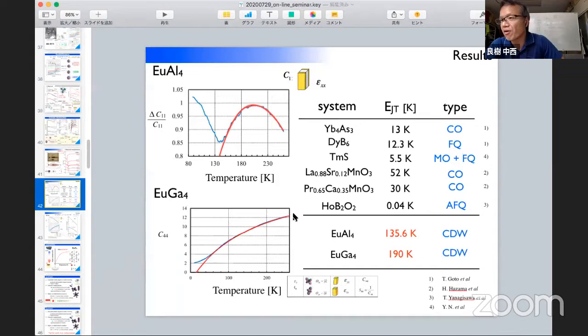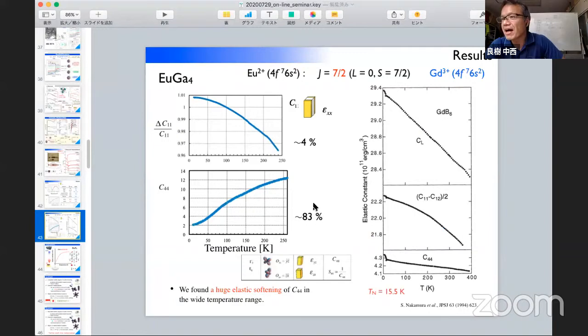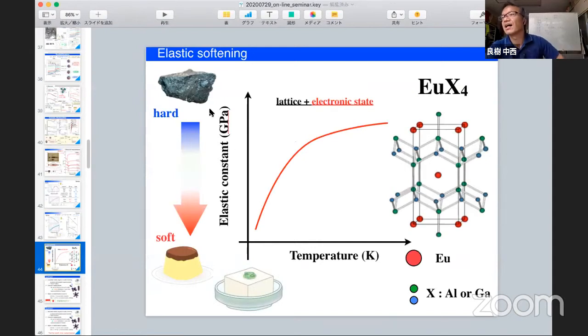In the case of europium gallium 4, it starts softening from room temperature. And almost 83% elastic softening was observed in europium gallium 4 in the C44, one of the principal elastic modes, as a function of temperature. So europium gallium 4 changes its elastic property dramatically at low temperature. At room temperature it is like iron, but at low temperature it changes its elastic property dramatically, like the famous sweet pudding or the typical Japanese food, tofu. So it's a really wonderful and fantastic behavior at low temperature.